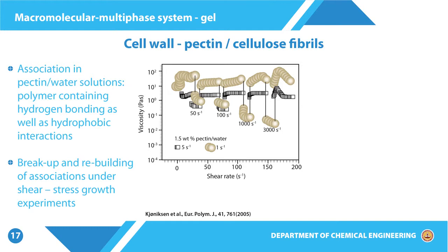but when both of them are together, in the case where there is cellulose as well as calcium, the properties of this pectin cellulose composite are higher. And the other thing to notice is that when both cellulose microfibrils and calcium are there, there is a stronger percolated network which is formed of the pectin and cellulose together to give us a more perfect gel like response, where moduli are not dependent on frequency, while in the other two cases there are relaxation processes which make both the moduli functions of frequency.